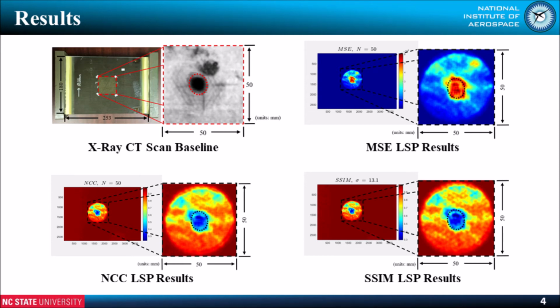We tested three different image correlation algorithms: mean squared error, or MSE, normalized cross correlation, or NCC, and structural similarity, or SSIM. For all three algorithms, the larger circle is the illumination area of the laser. Inside this circle, the baseline was overlaid as a black dotted ellipse. Evidently, all three algorithms were able to locate the damage quite well. Additionally, all the LSP results only took a few seconds to capture and process, making it near real time.